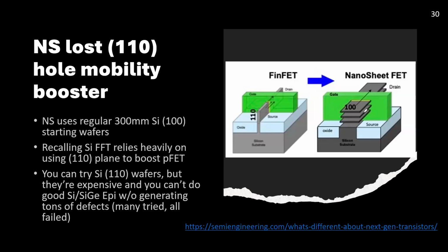So nanosheet used 110 surface, right? It lost the 110. It used 100 regularly. And so some people suggest, why don't you use a 110 flat wafer to begin with? I actually recommended that a long time ago. And it turns out I cannot do that, because the silicon wafer, when you grow it, you have a problem. You cannot grow 110 easily. You have to use a 110 seed to begin with, all right?